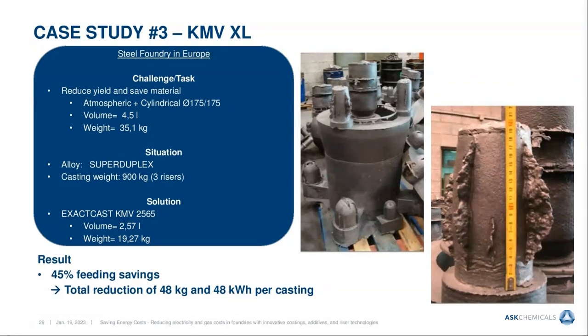In this third case study, we are talking about a super duplex casting, a special alloy in which the original design consisted of, again, traditional fiber solution, atmospheric plus cylindrical sleeves with a volume of 4.5 liters. And the solution was again to offer the KMV 2565, achieving feeding savings of 45%. In the end, the reduction of 48 kilos in this case meant also energy savings of 48 kilowatts per casting.